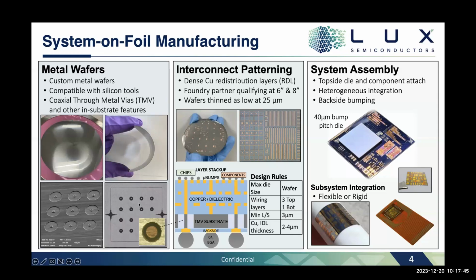We then can pattern the wafers themselves. And so what we're showing here is a through metal via. So there's a pillar of metal that is left inside of the larger metal substrate, and this donut area is filled with the dielectric to electrically isolate it. And so all your signal currents will run through the pillar, and all your ground currents will run through the grounded metal substrate. And so we show through metal vias here, but the core technology is capable of patterning any type of component in the substrate for different types of substrate functionality.